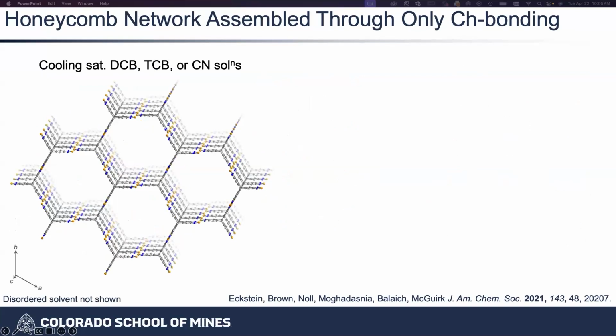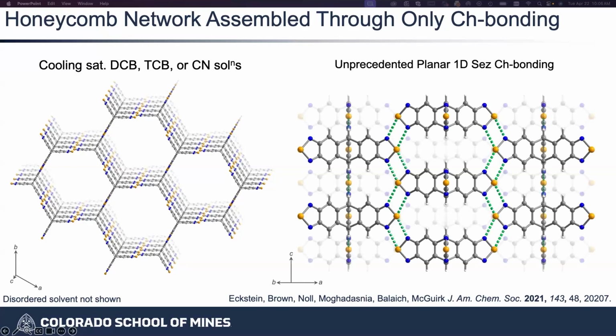We have this low density structure where there's 2 nanometer pores. There is the starter solvent in this structure, but the only contacts between those molecules in space are these selenium-nitrogen interactions. We got this structure